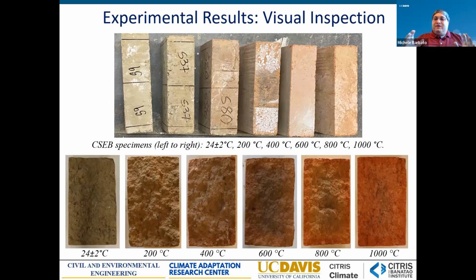Fundamentally, the color changed from a brown that is typical of unfired clay into the red that is actually more typical of fired clay bricks. And you can see here how this is proceeding from the outside, and with the 1000 Celsius, it goes through the entire depth of the block. These are the half blocks after testing for flexure.